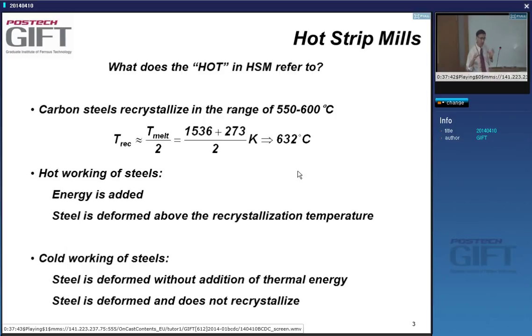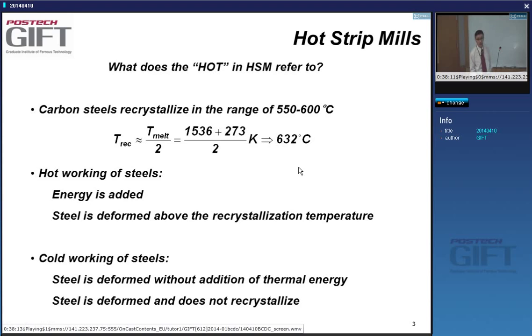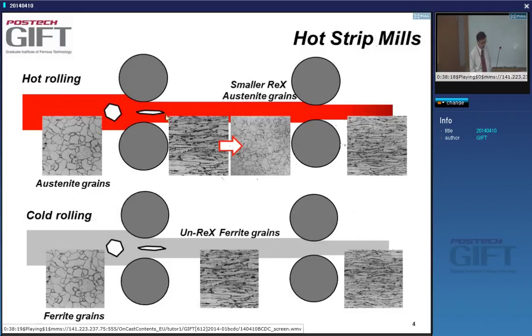The 'hot' in hot strip mill refers to processing above the recrystallization temperature — above 630°C. All processing in the hot strip mill is above this temperature, and very often the coiling temperature is around this value too. This means that between deformation steps, the material recreates a low-defect-density recrystallized structure. The hot strip mill design is very much determined by its original product mix — the mechanical, electrical dimensioning, and automation are all tailored to the intended products.